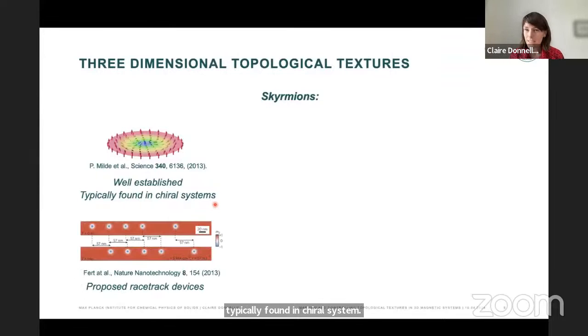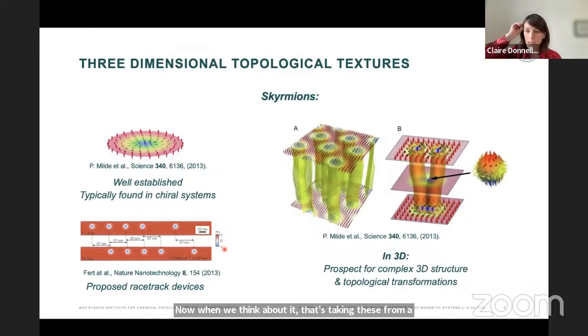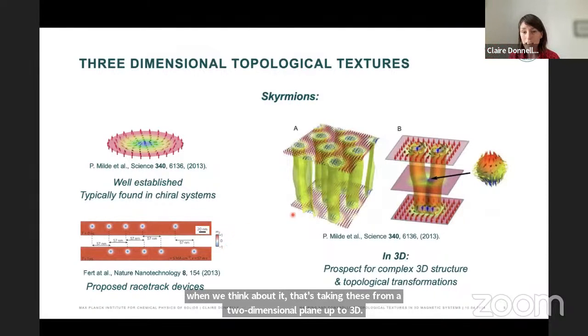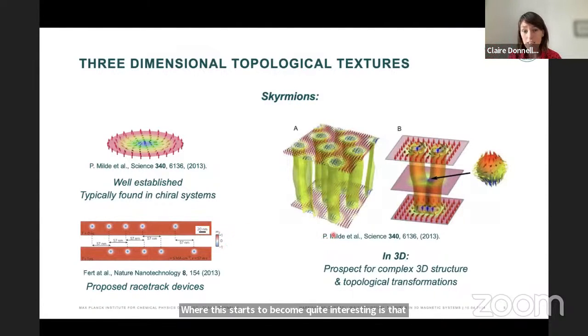And there have also been already a number of different devices proposed, for example, the skyrmion racetrack memory. Now, when we think about taking these from a two-dimensional plane up to 3D, where this starts to become quite interesting is that you can actually have topological transformations in 3D. So these skyrmions that exist in a plane can form skyrmion tubes. And within the thickness of a system, you can have transformations of the topology, where you see one skyrmion transform into two, associated with the presence of a Bloch point singularity.